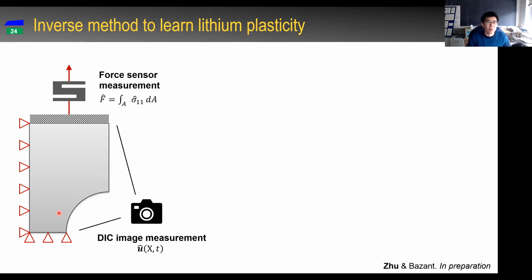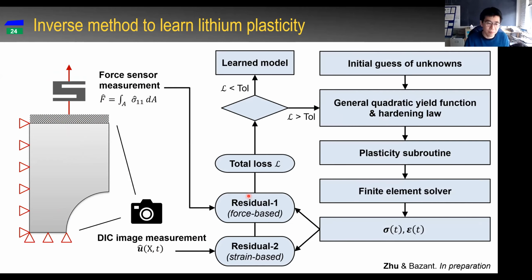Okay, so we started to develop this inverse method and apply it to lithium plasticity. This is, for example, one test that we can do, and we measure the force. When we do the tensile test, we can measure the force, which is the integral of the stress over one cross section, and we can use image data to measure the displacement field. Then we put it into the inverse learning algorithm.